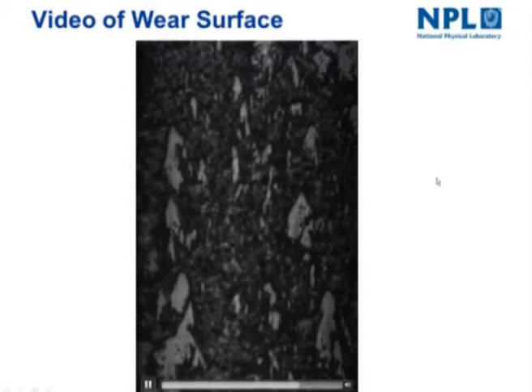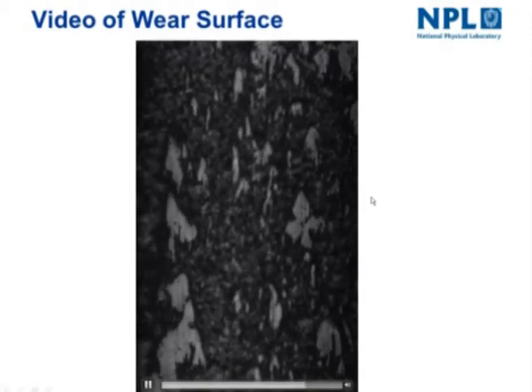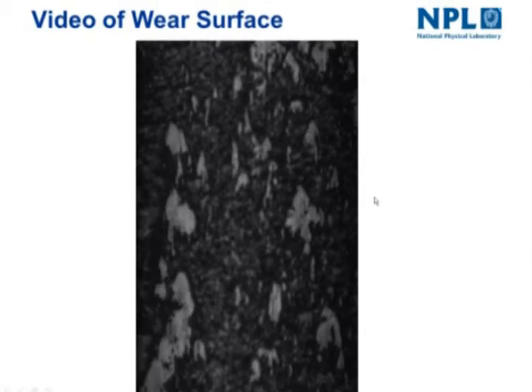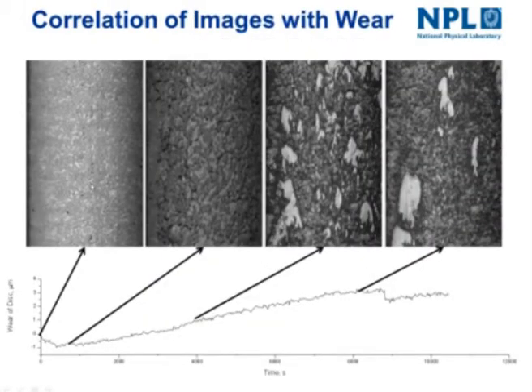I'm going to move on from that. It doesn't change that much for the rest of that video. But this just summarizes those results. So a still image from the start shows the original surface. Here we produce some pits in the surface. This is the low point of the wear to the disc. Here we're beginning to build up these layers which push the surfaces apart, and then this is towards the end of the test. This step here isn't significant, it's just an artifact in the measurement, but I hope you can see the power of that technique.